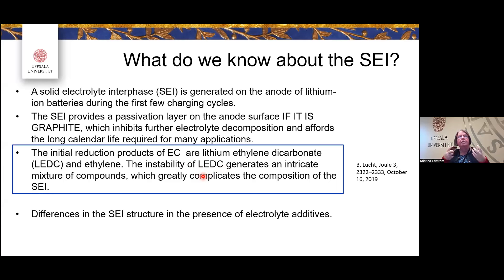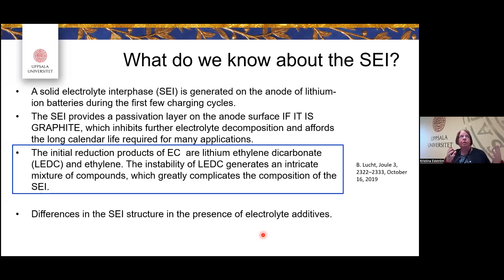Professor Brett Lucht from the University of Rhode Island suggests the main reduction product is lithium ethylene dicarbonate and ethylene gas. The instability of this LEDC generates the large mixture of compounds that complicates the SEI composition, making it so intriguing that many different reaction mechanisms have been proposed. There are also many additives, and the presence of electrolyte additives affects the SEI structure and morphology. Remarkably, adding just one or two percent of something can make a significant difference.